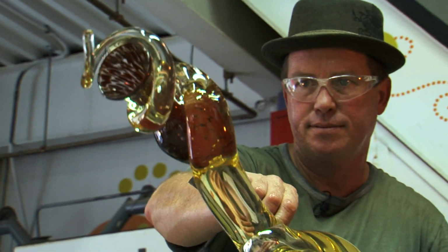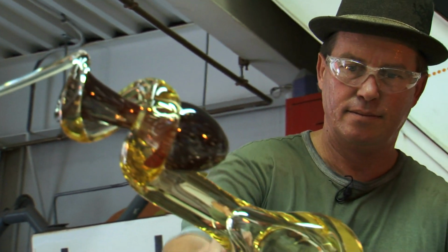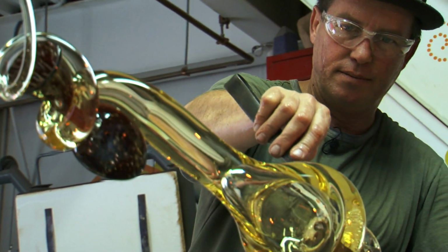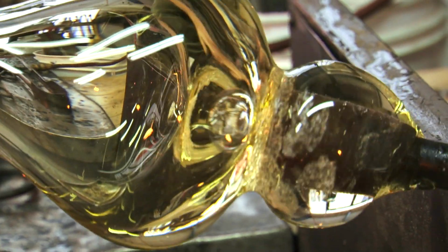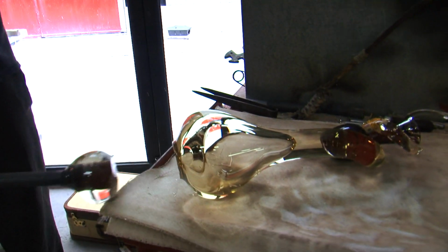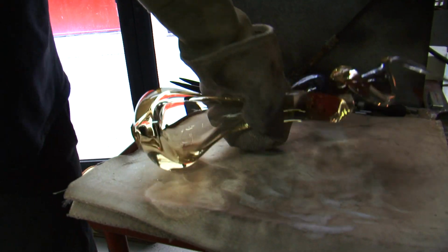And then we pour water on that neckline that we created earlier, and that makes it cold instantly. What we're trying to do is get it to crack along that line, the neckline that we made, by getting just that little zone, that little quarter inch, all the way around below 800 degrees where it wants to break. And everything else being up by the softening point where it cannot break, it physically can't. At that moment where we think it's stressed correctly, we tap on the pipe and the vibration sets off an earthquake within that cold spot, and it will crack off.